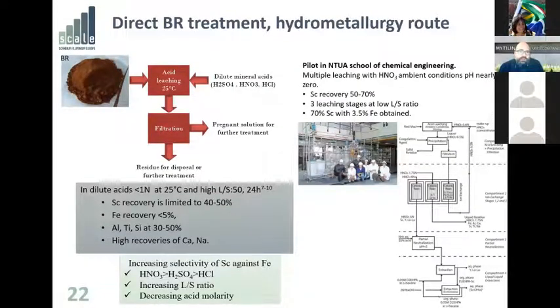Another process is the acid direct bauxite residue hydrometallurgical treatment, where you go for acid leaching with dilute mineral acids at ambient temperature. You filtrate and you have a pregnant solution for further treatment and a residue for disposal. So in contrast to the previous Rusal technology, which operated in the alkaline region, a region that is more close to the alumina production cycle, now we're moving to the acid side. Here, scandium recovery, for the Greek bauxite residue, can go up to 40 or 50%. Iron recovery can be less than 5%. And aluminium, titanium, silicon are reported between 30 and 50%, while calcium and soda are fully recovered.